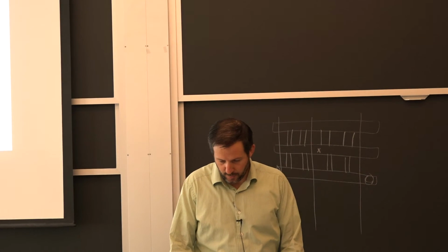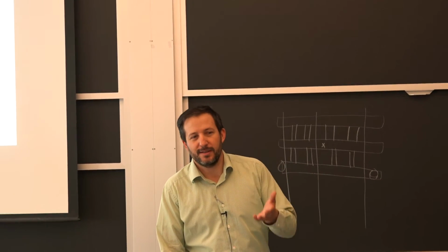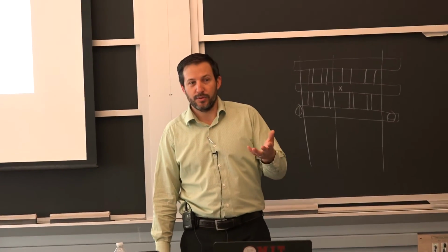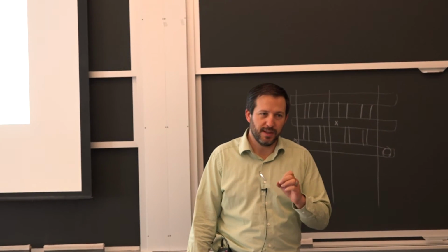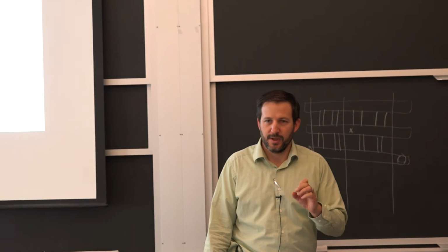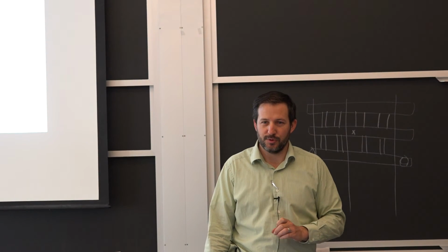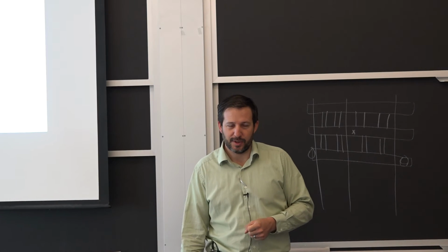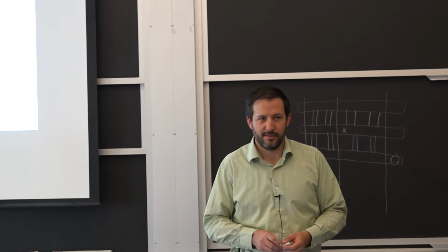The point I want to make is it is not the steel. By the weight of it, it doesn't weigh the weight of the steel, so it is the corrosion product that built up and expanded. So it's about 3 to 4 times bigger in volume than the original steel that was used to make it. So it's not too bad for the application. Yes? Oh, I thought there was a question.